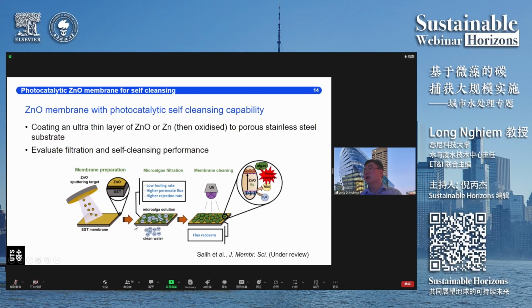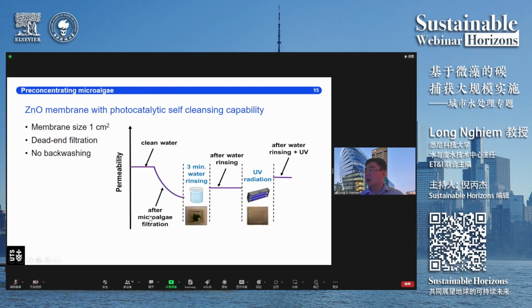Now that zinc oxide has photocatalytic property, as I will show you later when I show you data of the membrane characterization. And with that photocatalytic property, basically when we shine a UV light onto the membrane surface, we can initiate the photocatalytic function, and then it becomes a self-cleansing process, which is very effective to do the membrane cleaning that addresses the problem that I mentioned earlier, that there's some residual fouling on the membrane. So we have demonstrated that recently.